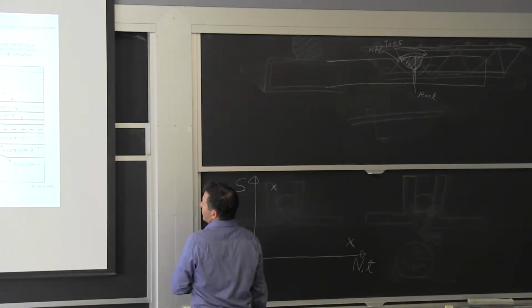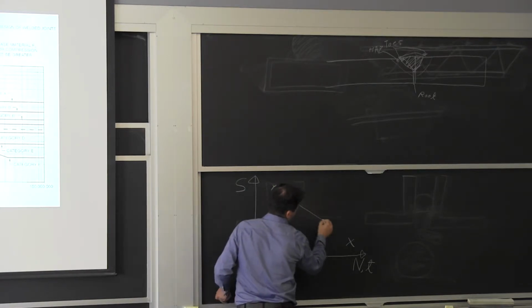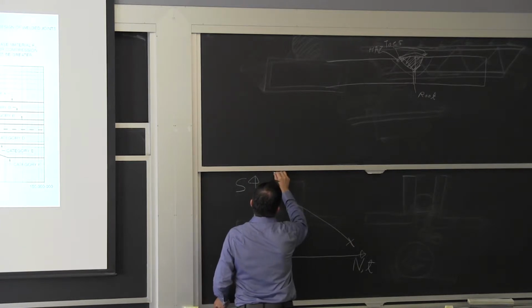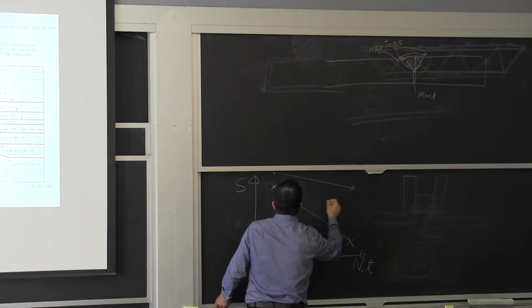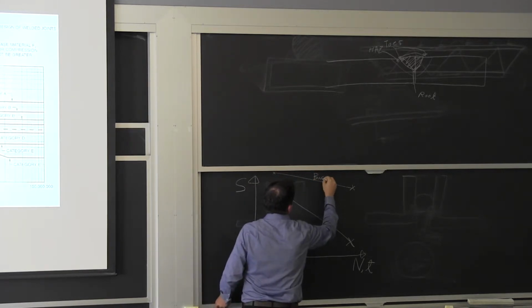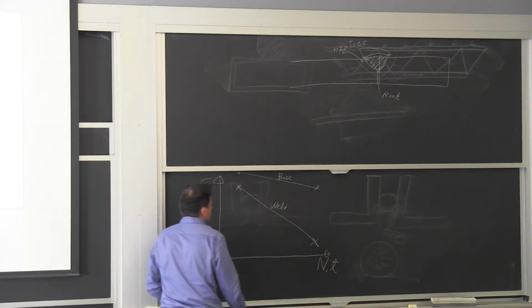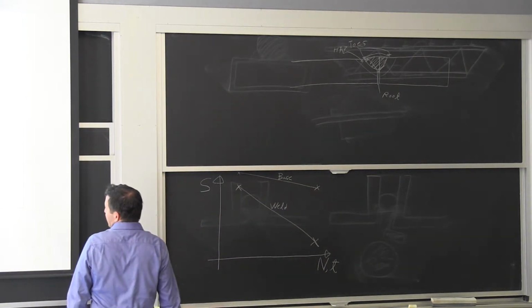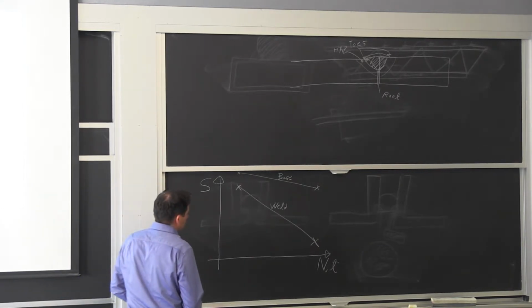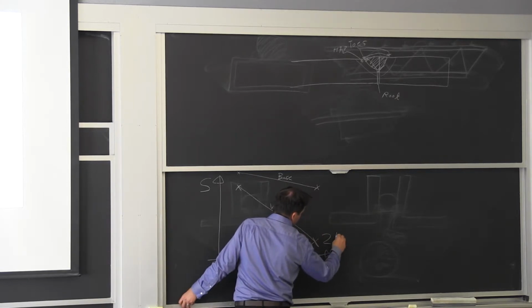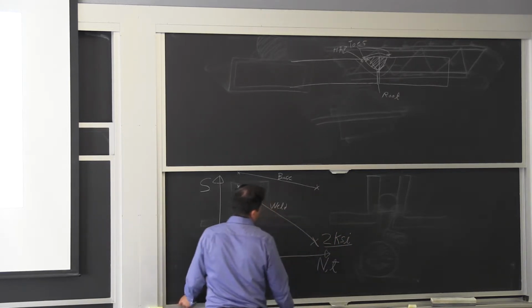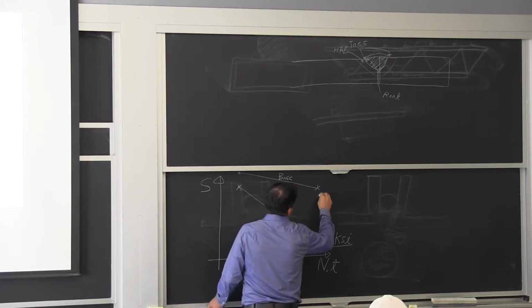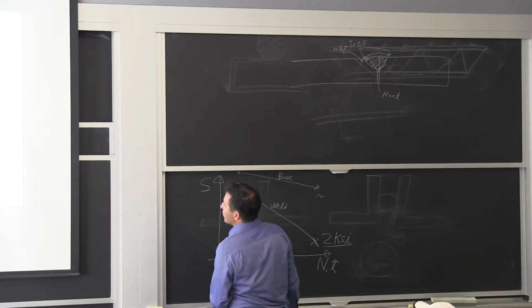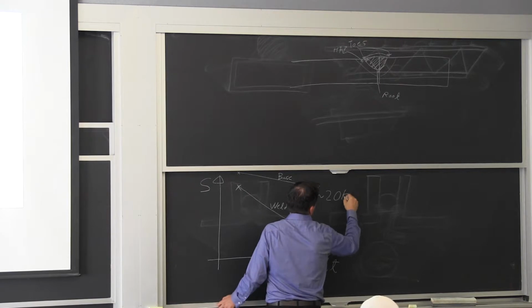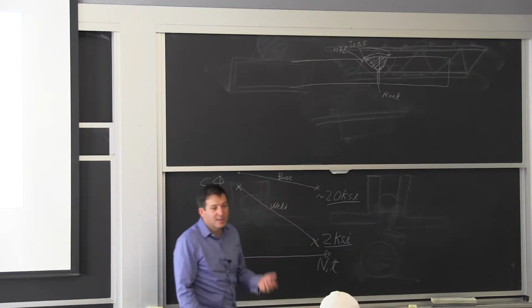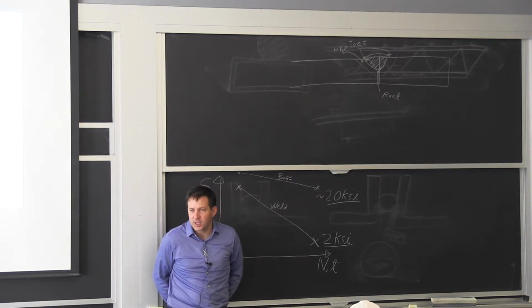And you have it here for a number of conditions. Say we do the weld first down here, and then we'll do the base material over here above. So base, and then the weld. That's typically how it's going to look. A typical value here for steel in the worst scenario, you're only able to put about 2 KSI stress as your allowable. And if you have a base material of steel, you're looking more at 20 of that. Even more, but let's put 20. So what happened? I lost a factor of 10 in my allowable stress for design.